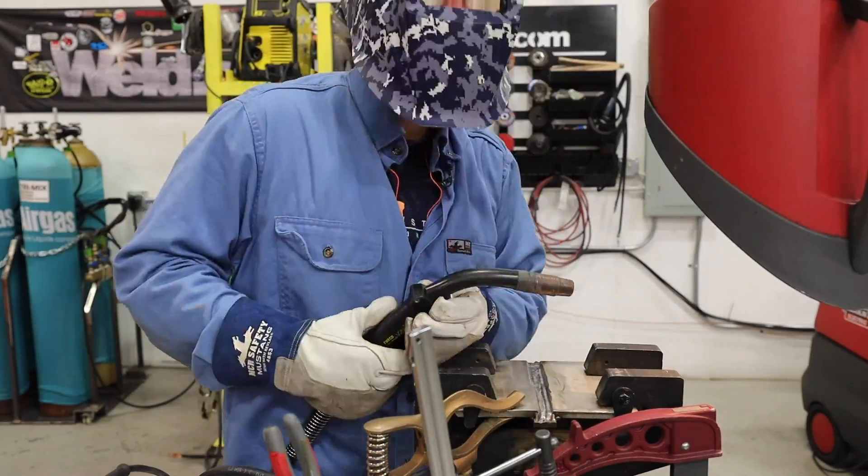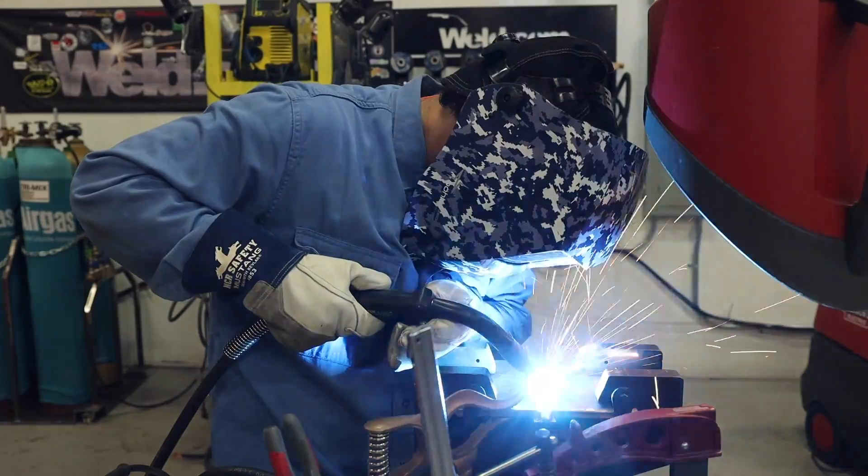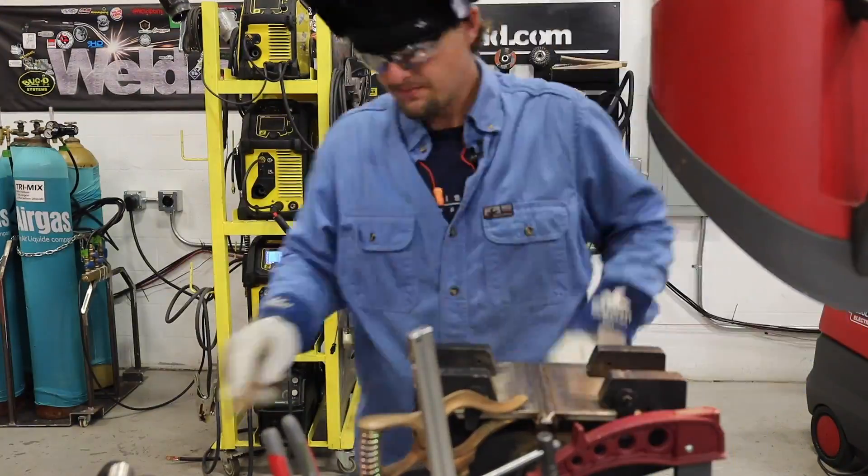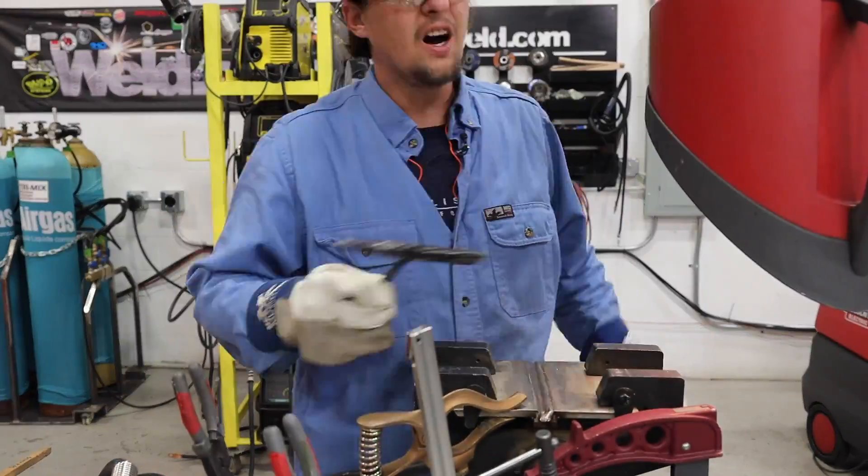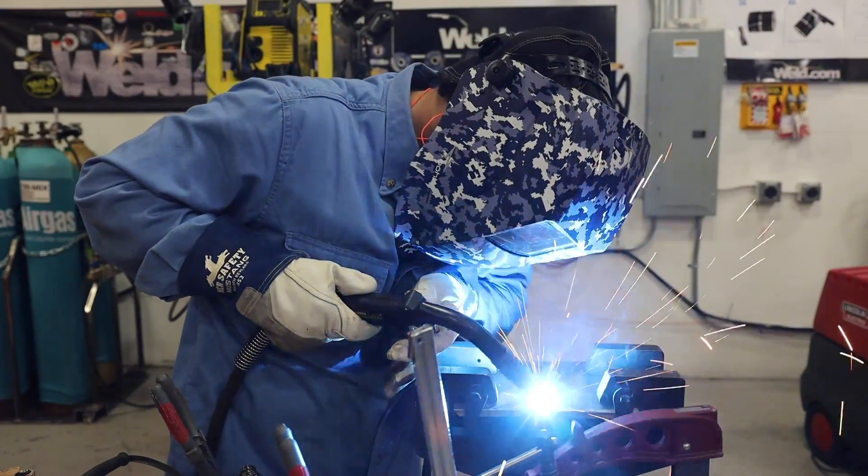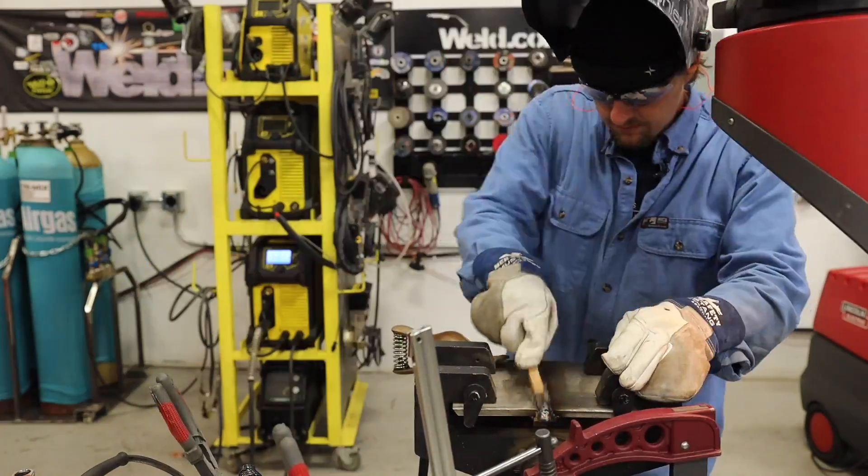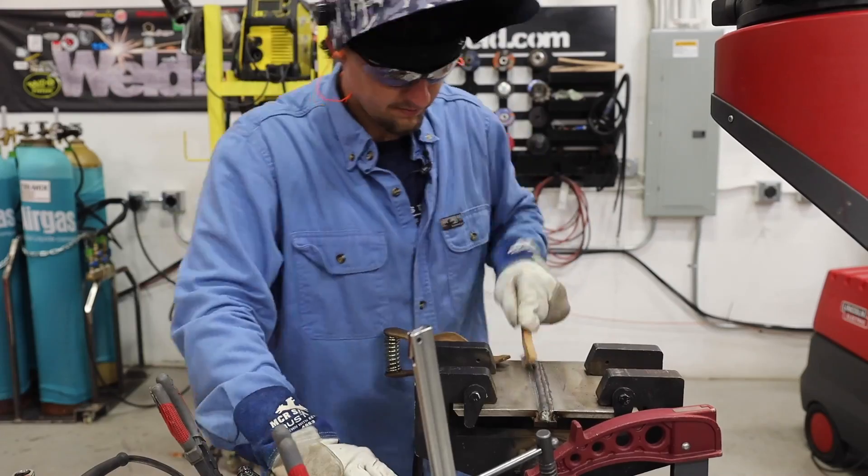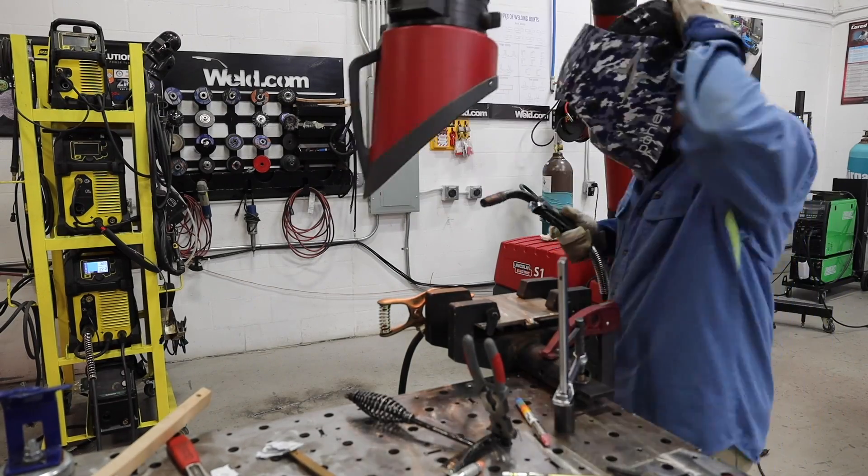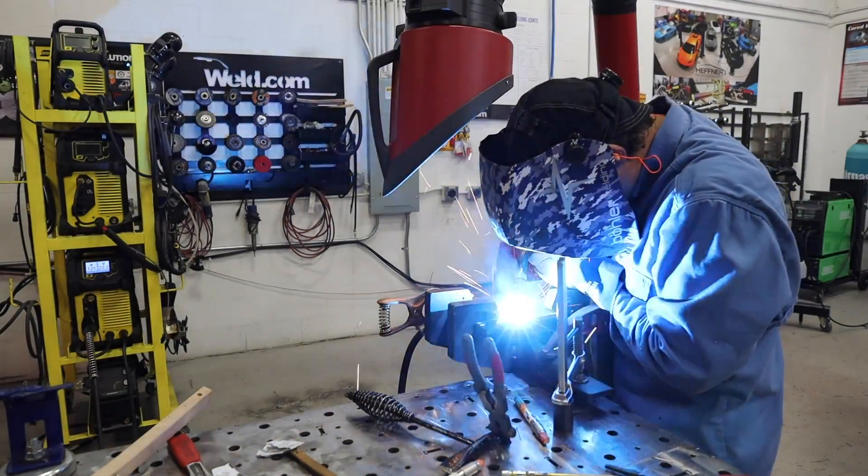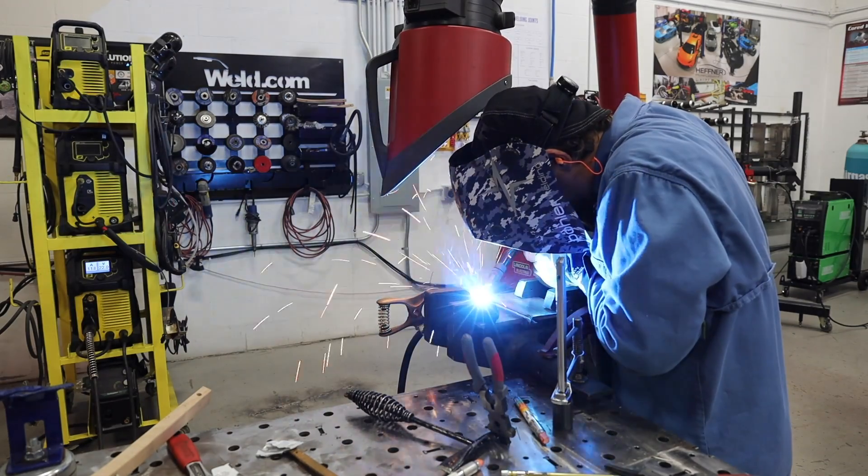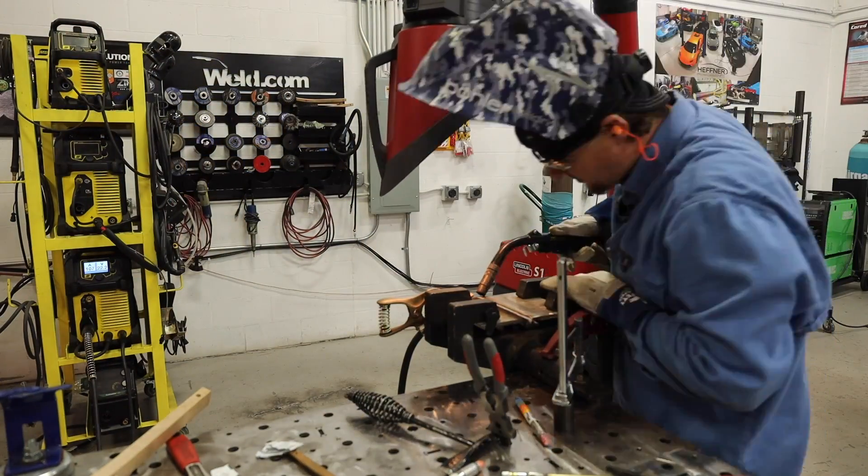I think that's pretty cool enough. So we're almost to the cap. We're going to do one layer of fill pass. So I'm going to do four quick beads or quick stringers. And I want to do no slow because it's going to hump up too much. Then my cap's going to be above eighth inch. So we're going to do four quick ones. Make sure I'm tied in. Grind my toes. And that's it. We're going to make sure we're waiting in between passes a couple minutes. I try not to let my inner pass get hot, right here where you're running inside your bevel. But I always check in a couple spots. So I'm under 200. So I'm going to go ahead and just go ahead and keep running it and make sure it's 200 in between each pass.